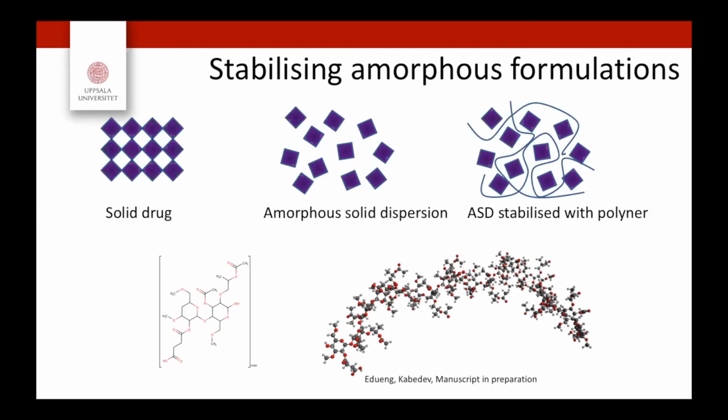So even if it's not within the liquid, but rather in the storage room somewhere, it would tend to form again this semi-crystalline structure, where it would be less soluble. It is made amorphous to be more soluble, but if you leave it for a long while, it will get back to something similar to the solid structure. For that purpose, there are several techniques for how it could be stabilized, and one of them is the introduction of a polymer.